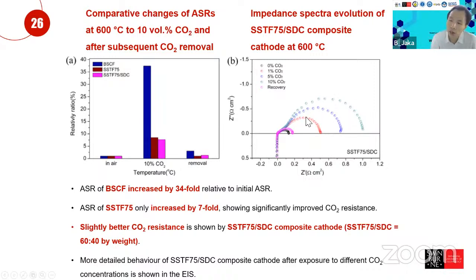And this shows the composite cathode, what happens after it is exposed to 1% CO2, 5% CO2, 10% CO2, and then after the CO2 is completely removed compared to the beginning. So we start from here, the area specific resistance. As we expose 1% CO2, the area specific resistance increases. 5% CO2, the area specific resistance increases, then 10% CO2 it increases, because obviously when you put in CO2, the CO2 will be adsorbed on the surface of your cathode, and that will basically block the oxygen reduction reactions on the surface of your cathode. But as the CO2 is removed, you can recover about the same performance as your original performance, which means that although the adsorption happens, the CO2 does not react with your material, which means that your material is very stable.